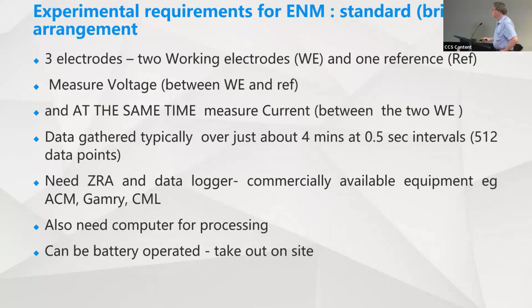So what do you need for the standard methods? Well, 2 working electrodes and a reference. I suspect most people have come across it to some extent in the past. There's data gathered over about 4 minutes at 0.5 second intervals. You can continue to do this, and the work back in Bierwagen's lab was done with continuous measurements, so you could see almost continuous data, or once an hour for 2 days or 5 days or whatever. If you're talking about using it for, say, salt spray testing, you can take it out every so often and test it.